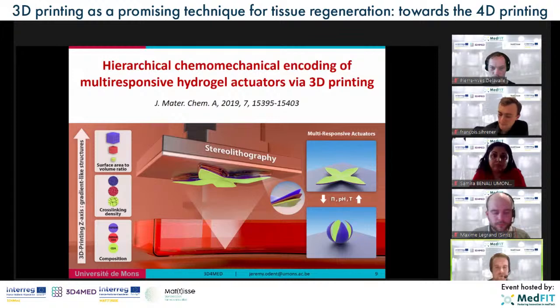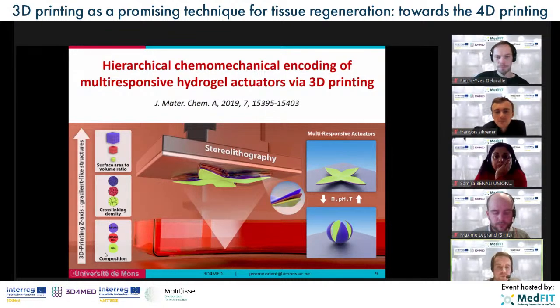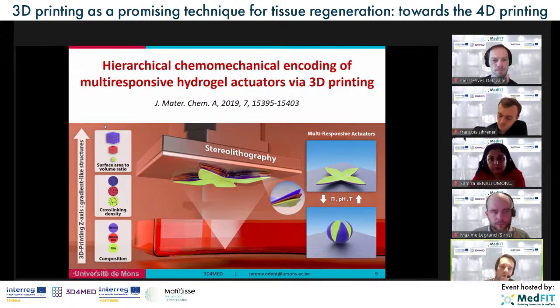Inspired by nature, we also demonstrate a family of multi-responsive hydrogel-based actuators that are this time endowed with anisotropic swelling behavior to provide rapid and controllable motion. The strategy to develop such multi-responsive hydrogels is based on the fabrication of gradient-like structures, where each individual building layer has a different chemical composition. We can have different cross-linking density or different surface area to volume ratio along the printing direction. So we are able to get control over the motion.